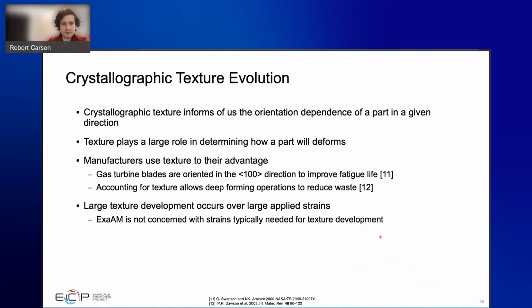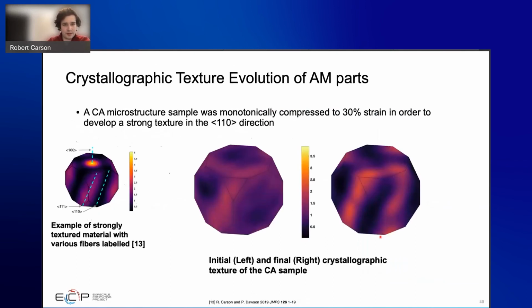I'll just skip over these next two. As I mentioned, you can capture crystallographic responses in the material. This is showing the initial crystallographic texture, and here it is after we deform it hugely. We see that our material does start evolving its orientations, and we start seeing a much more anisotropic response from the material over time.